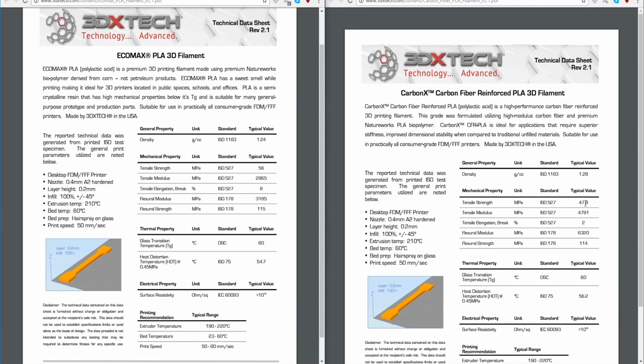So here we're also kind of seeing if that myth stands up, that carbon fiber actually helps the material, is actually reinforcing the material. So carbon fiber, 47.9 megapascals, and you notice that is ISO 527 standard, so exact same. So everything in here is the exact same standard, so we could compare apples to apples here, and exact same properties. So 47.9 to 56. So PLA is already higher ultimate strength before breaking.